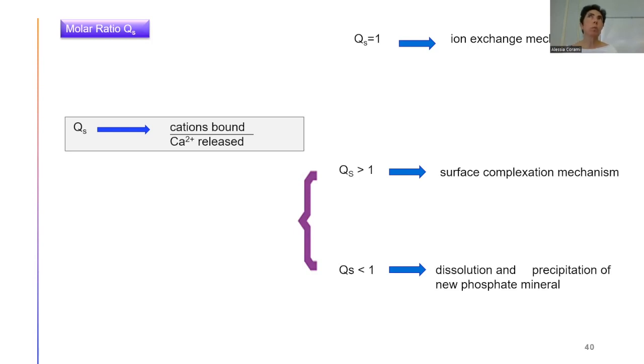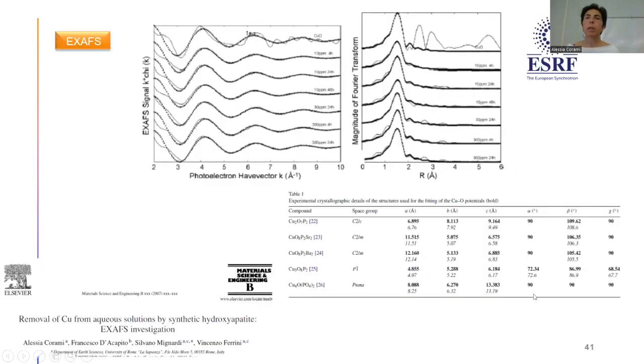But there are 2 points that we have to remember. First of all, when we have different contaminants in solution, each contaminant could choose a different way to be immobilized by the phosphate. So it's not simple to understand the immobilization mechanism. And in particular, in our case, when you observe that the phosphate, after the contact with the metals, can precipitate with a shape equal to the original shape of the amendment, it's quite difficult to understand if you have the dissolution and precipitation mechanism. So then we went to the European synchrotron in Grenoble to analyze this behavior and to better understand if our hypothesis could be correct or not.